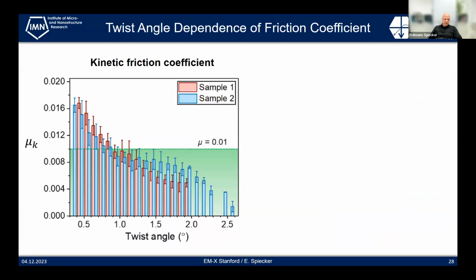And you see that at a twist angle of about 1 degree, the kinetic friction goes below 0.01, which is sometimes stated as the border to kind of superlubricity regime. Unfortunately, we were not able to kind of explore twist angles smaller than 0.5 degree because already during the first sliding event, the whole system moved to these larger twist angles, probably because of this incommensurability, because as soon as you have individual dislocations, it might be energetically unfavorable to stay there, but to make another twist to reduce the friction force.